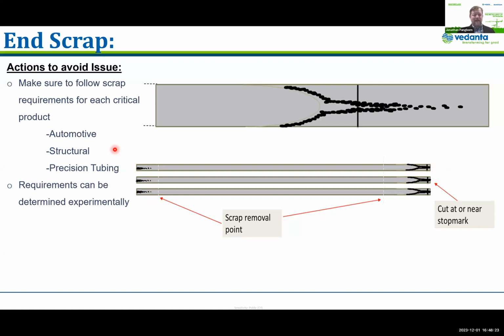These requirements can be determined experimentally quite easily, actually. For example, if you go from your stop mark and cut periodically, whatever makes sense for you, every 10 centimeters or every 20 centimeters, and etch it even in your caustic, if it's fairly fresh in your die shop, you will be able to see this and make some judgments on what's acceptable experimentally, and then making sure that it's followed and that your press crews understand the reasons for that, so that you avoid risks downstream.